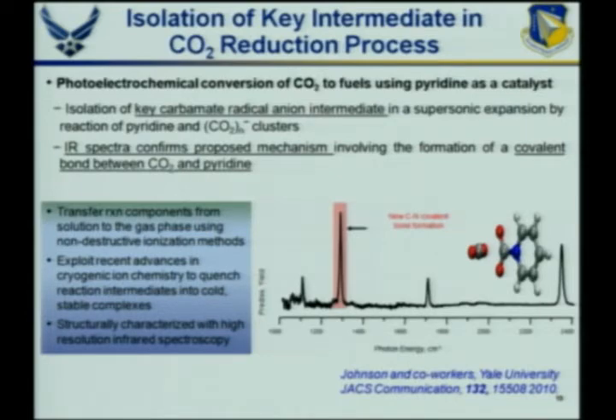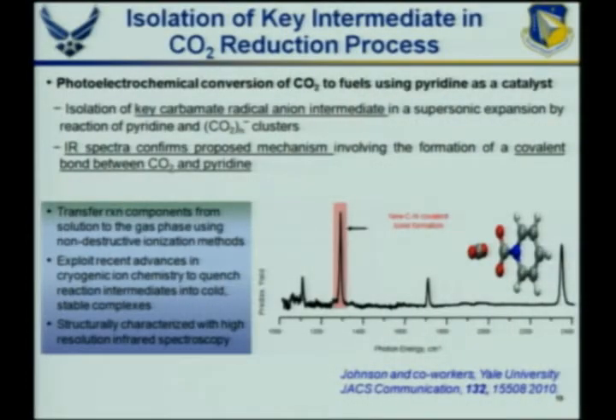It's kind of an experimental tour de force, but Mark was able to do this using some electrospray methods to put these gently into the gas phase, into a vacuum system, and using some advances in cryogenic ion chemistry to quench these intermediate species and take very high resolution infrared spectra. And in fact, we were able to see this new band arise due to this carbon-nitrogen bond that was formed by CO2 bonding to this pyridinium ion. So for the first time, they've been able to identify that this is a stable species, give the people doing electrochemistry important information on the mechanism, and then give them a tool now, a spectroscopic signature that they can use to probe this in real time in their electrochemical experiments.